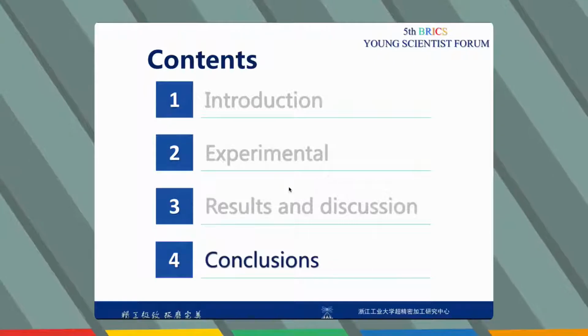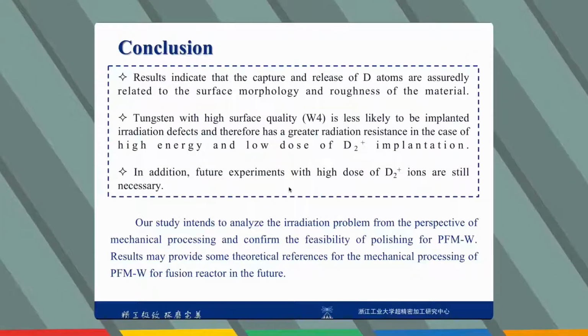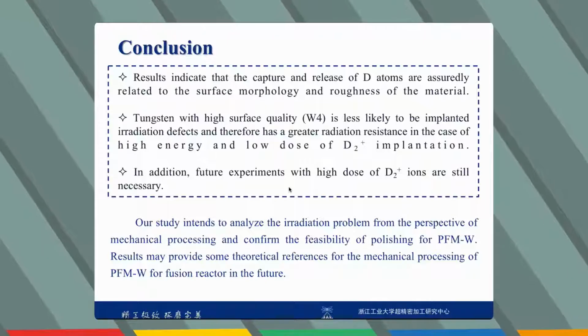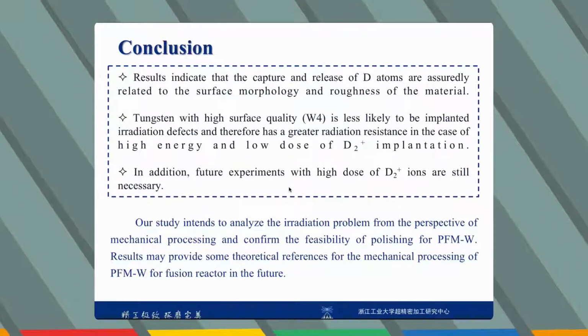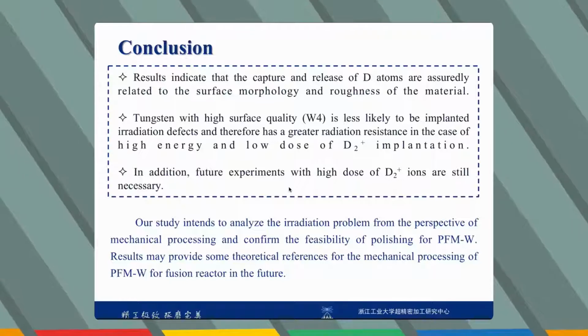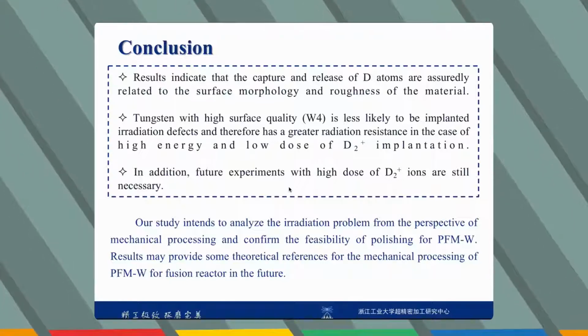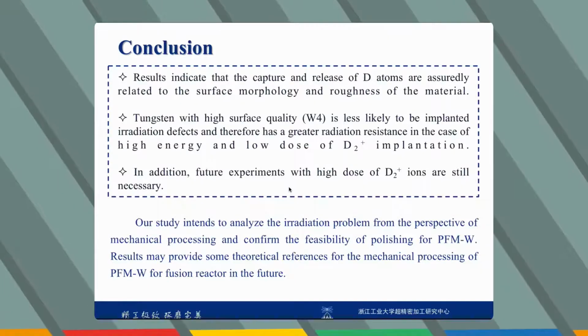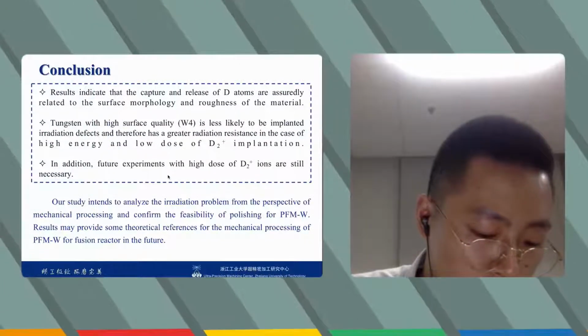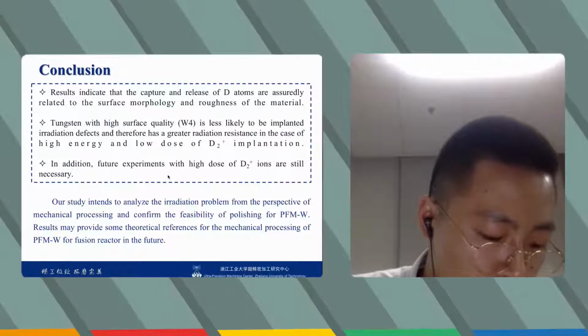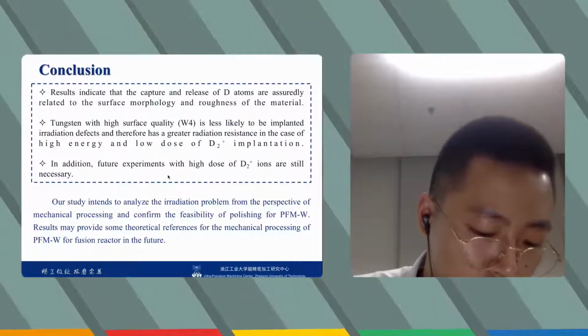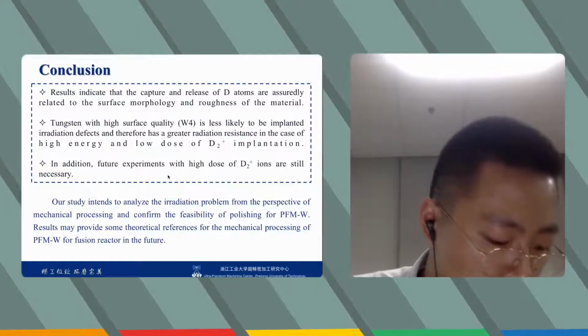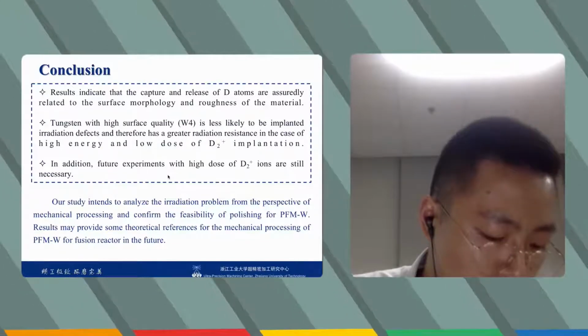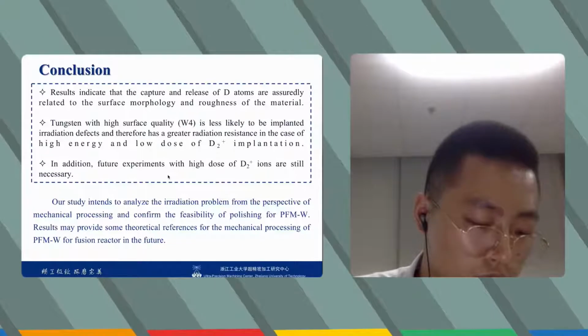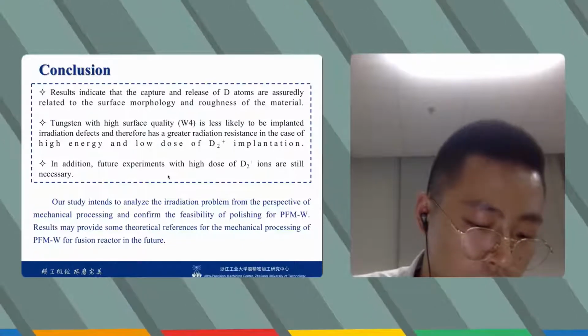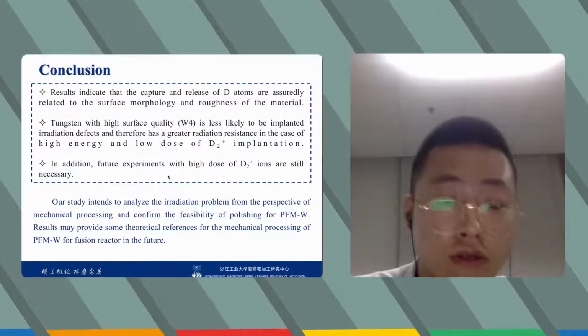And finally, I would like to make a conclusion. Results indicate that the capture and the release of deuterium atoms are assuredly related to the surface morphology and the roughness of the material. Tungsten with high surface quality is less likely to be implanted in radiation defects and therefore has a greater radiation resistance in the case of high energy and low dose of deuterium implantation. In addition, our future experiments with high dose of deuterium ions are still necessary.